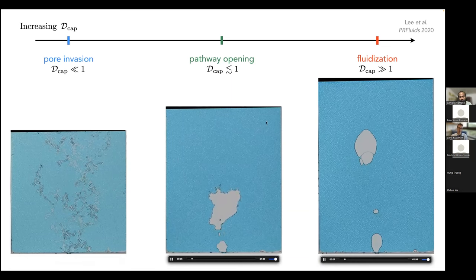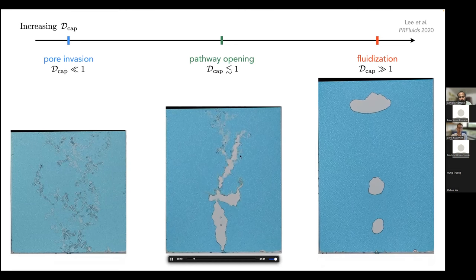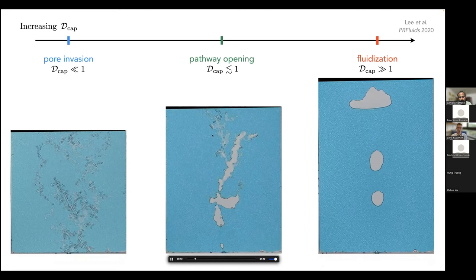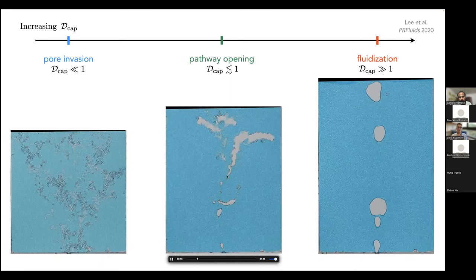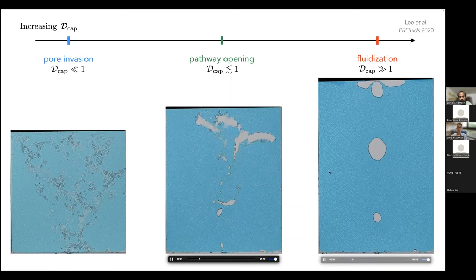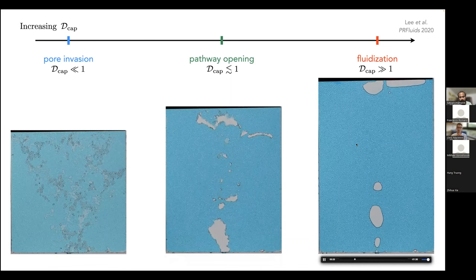So this porous medium, because it's granular, when you confine it a bit more, develops a bit more stiffness, and it tends to deform through fracture. So it behaves a little bit more like a brittle elastic material. Whereas when you confine it a bit less, again because it's granular, it starts to behave a little bit more like a fluid. So the grains can flow and rearrange.